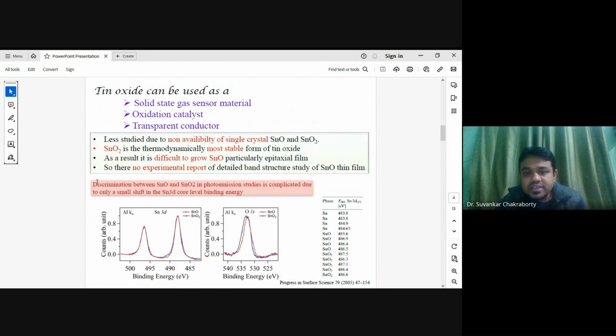But this material is very little studied because of the non-availability of single crystals of SnO or SnO2, and it is very difficult to grow epitaxial film so that we can study the electronic properties. And in addition to that, most importantly, generally when we grow a thin film, we differentiate it with XPS because it has different oxidation states. Sn has two oxidation states, Sn2+ and Sn4+.